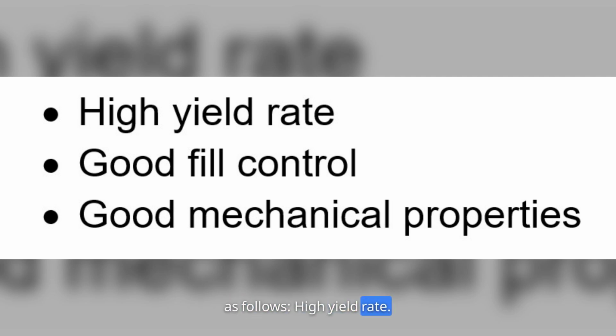The advantages of the PCPC process are as follows. High yield rate. This translates to lower operating costs, reduced melt loss, and less material handling. Good fill control. Fill is controlled by programmed pressure curves, and precise fill dynamics can be achieved. Good mechanical properties. Properties are typically better than sand, gravity permanent mold, and low pressure.